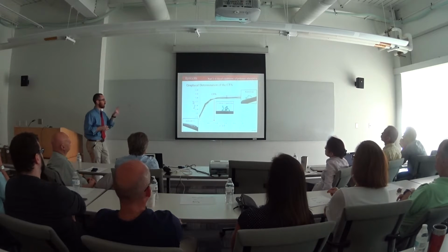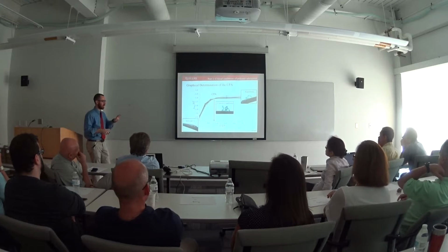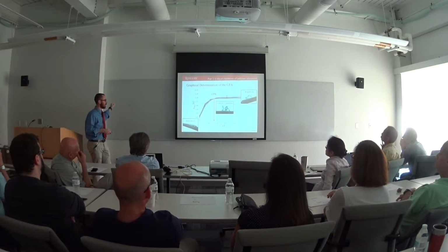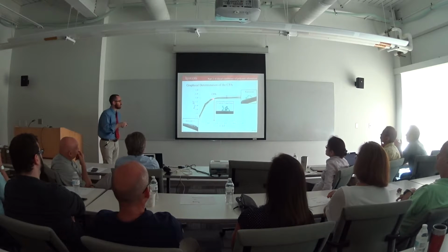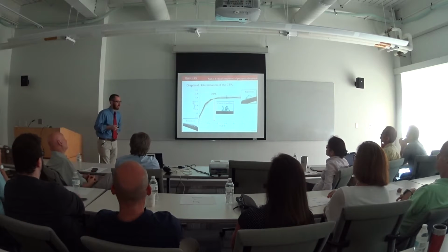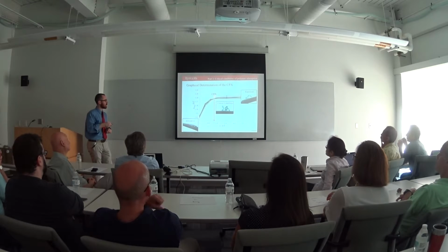We can also graph this in the following manner. So this is our surface adsorption potential. This is normalized to a different value than we had in the previous figure. And this is the incremental chemical potential. These are for different chain lengths. And what we expect and what we find is that at the critical point, we have independence of the critical conditions on the chain length, denoted by the crossover of all the functions. And this crossover point points out where our critical adsorption potential is.